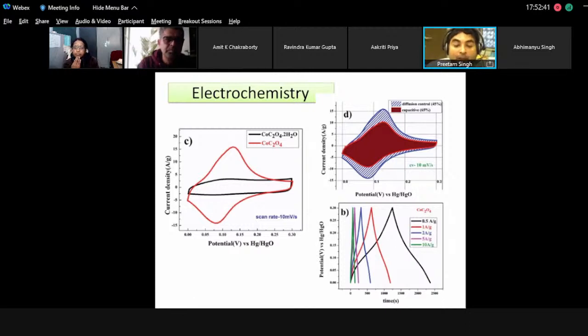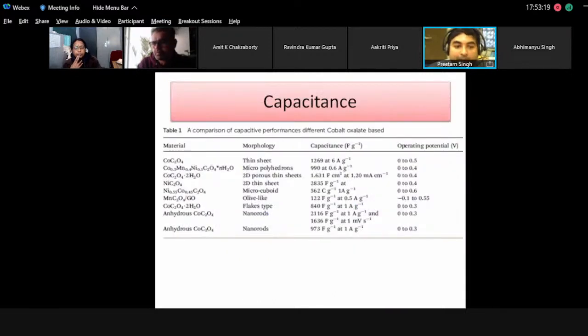And see, these materials have performed with an energy density much higher than normal capacitors, and they perform like a battery. This material itself has a capacity close to 100 milliampere hour per gram. If you see this charge discharge profile, the timeline is 2500 seconds, or about 20 minutes, of charging and discharging at half ampere per gram current rate. And if you see the detailed electrochemical mechanism, we are seeing almost 45% diffusion control and 55% capacitive control over the material. So it is ideally a half battery, half capacitor kind of thing.